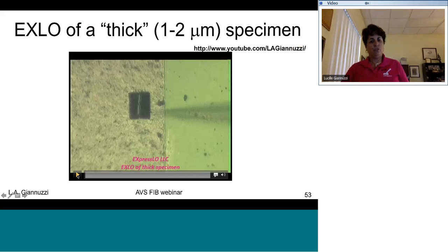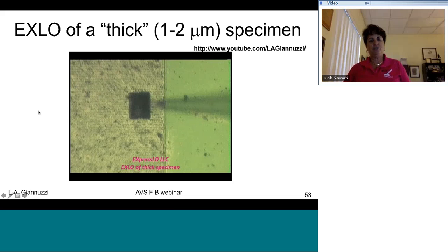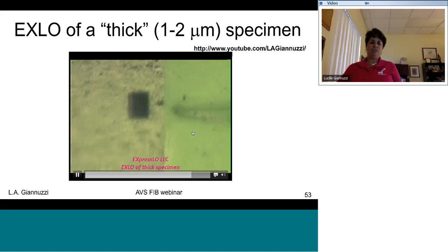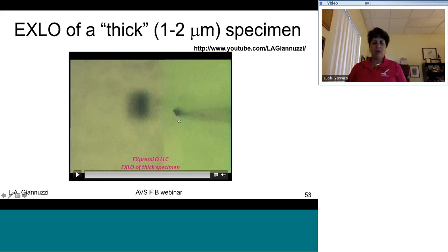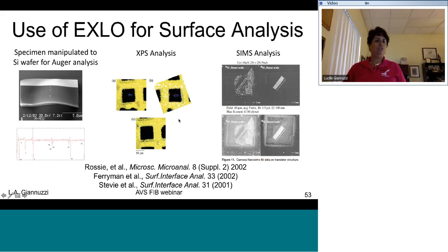So you can also lift out thick samples, so very easily polish a sample up to 1 or 2 microns thick. And that was real time, by the way, so just in a few seconds you can get a thick sample out and quite specifically do, for example, SIMS, XPS, Auger, etc. So it's a really fast and easy way to lift out any sample that you want to analyze without having to get it electron transparent.